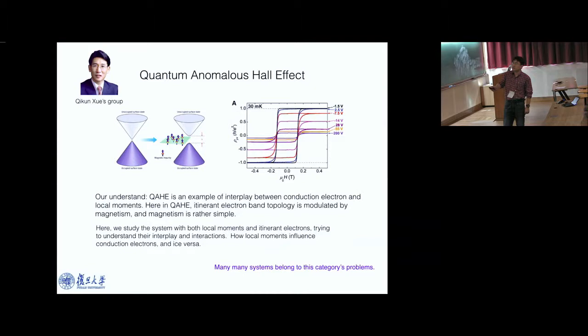And if you tune your Fermi level, your chemical potential, to be in the middle of this conduction band and valence band, it turns out the valence band has a non-trivial Chern number, has a Chern number equal to 1. So then you will observe an integer quantum Hall effect. You get a quantized anomalous Hall effect. This realizes the original idea of Duncan Haldane, where he tried to realize quantum Hall effect without a magnetic field. So this is an example of realizing quantum Hall effect without magnetic field. This is what they call the quantized anomalous Hall effect. So what I just described is the conventional understanding.